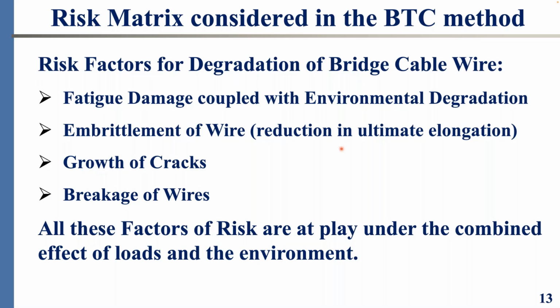So what are the risks of degradation that we try to capture and prevent or circumvent, so that they do not evade us, to stay ahead of these forms of degradation? Fatigue damage that's coupled with environmental degradation, what we dub in scientific terms as stress corrosion cracking and corrosion fatigue, which is a process that has nothing to do with the visual corrosion that you see on the surface of a wire. The embrittlement of the wire, which is a reduction in the ultimate elongation or reduction in ductility, the growth of cracks, and finally the breakage of wires, which is the worst thing that can happen to a wire. All these factors of risk are at play under the combined effect of the load and the environment.